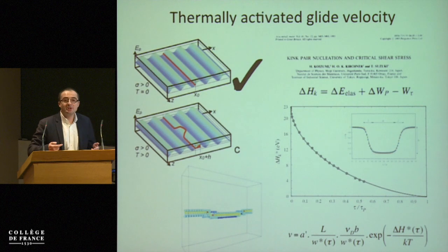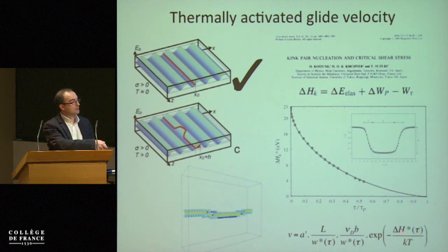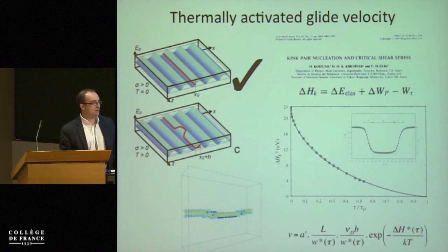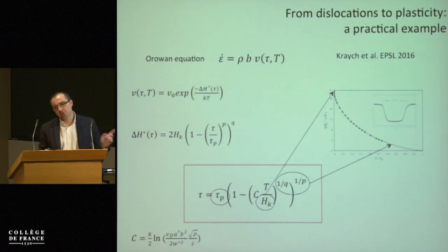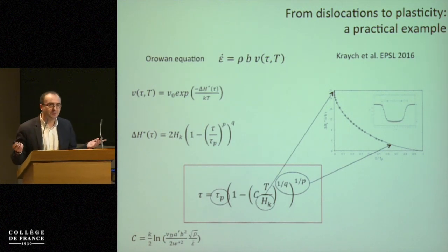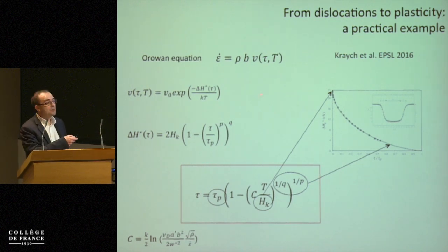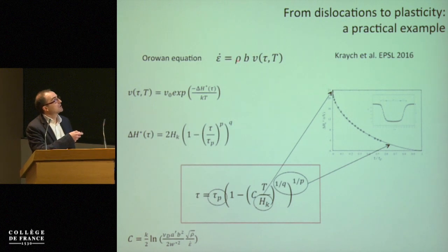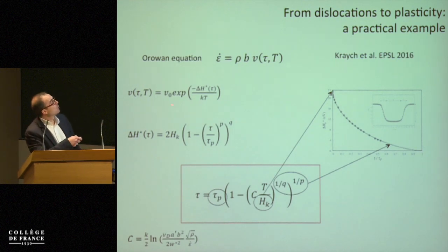The velocity comes from the probability of kink-pair nucleation, given by an exponential term where we plug this extra energy, with a pre-exponential factor corresponding to the attempt frequency of the process. So we have a velocity for dislocation glide. To go further toward plasticity, there is an equation linking the strain rate to the dislocation velocity: strain rate equals the number of dislocations times the Burgers vector times the velocity.